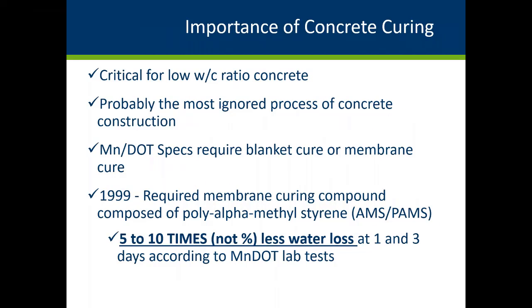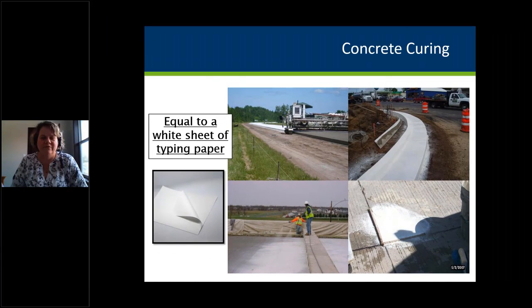In 1999, MnDOT switched to using the polyalpha methylstyrene curing compound versus the wax-based and water-based curing compounds that we'd used previously. And once again, with concrete curing, you can write specs that say what you really want them to say, but MnDOT went one step further and we have actual language in our spec that says how to place the curing compound. We do have a coverage rate, but we say equal to a white sheet of typing paper. So it's a very easy tool for the inspector to use when they don't see uniform curing that's bright white on their concrete. And overall, statewide, for many of our concrete applications, we have seen a great improvement in the curing.